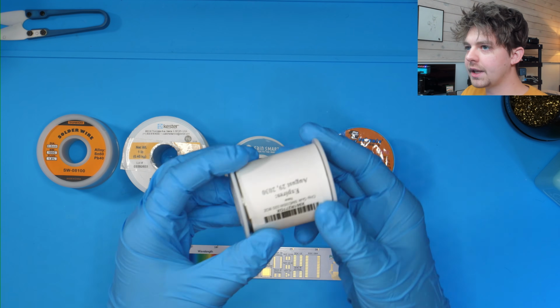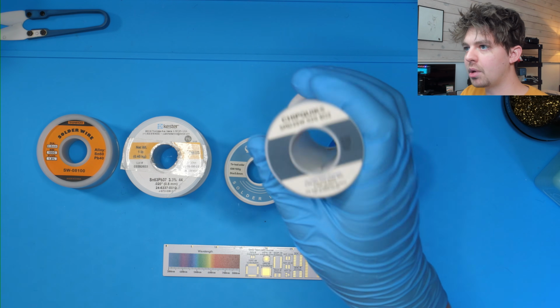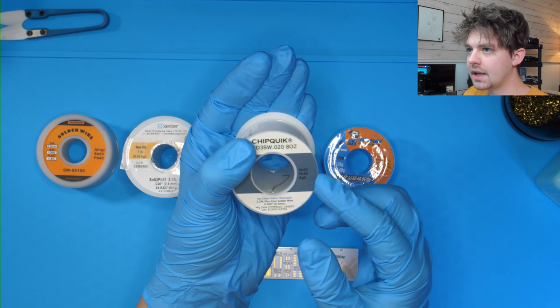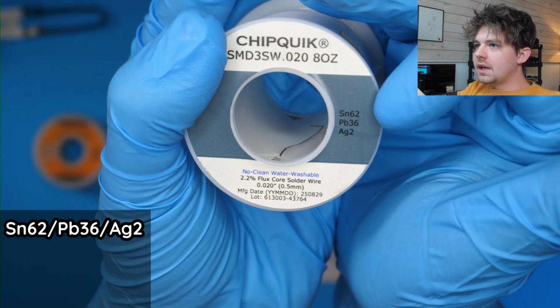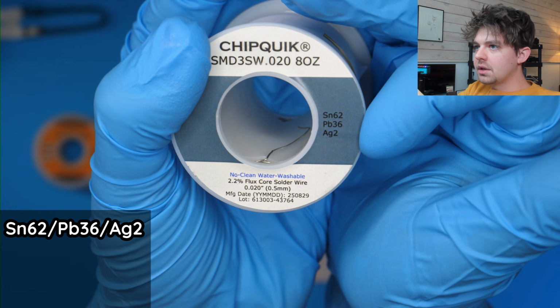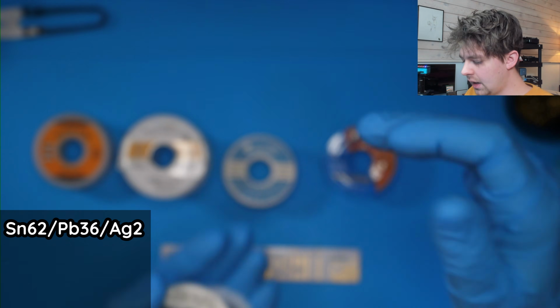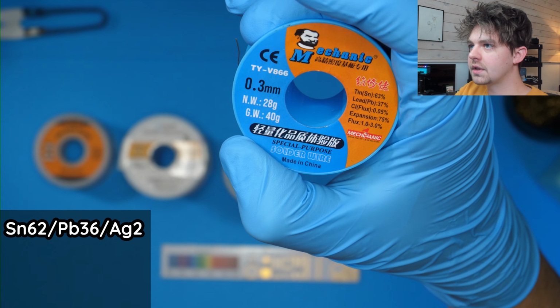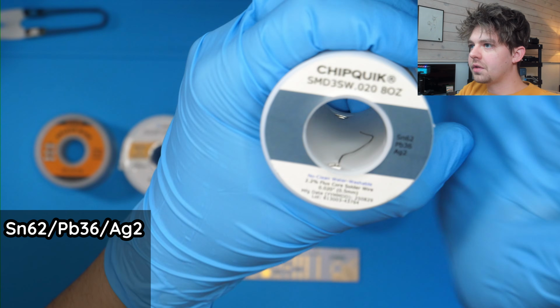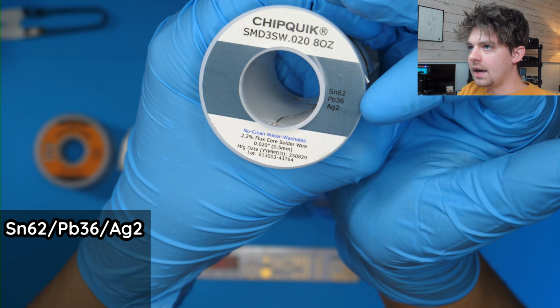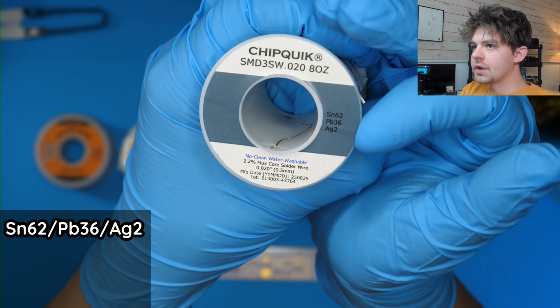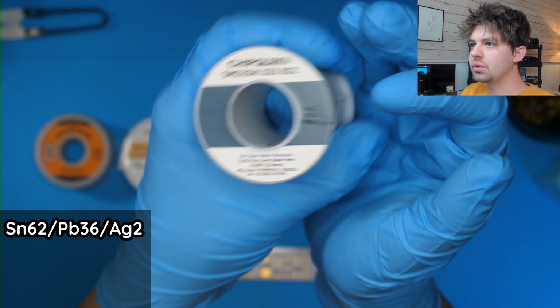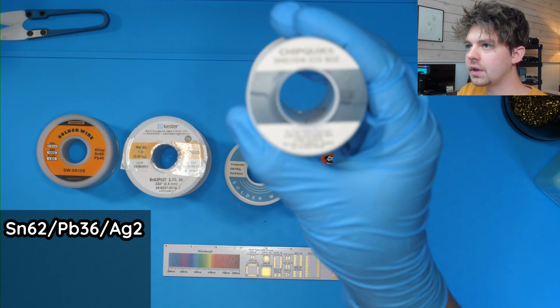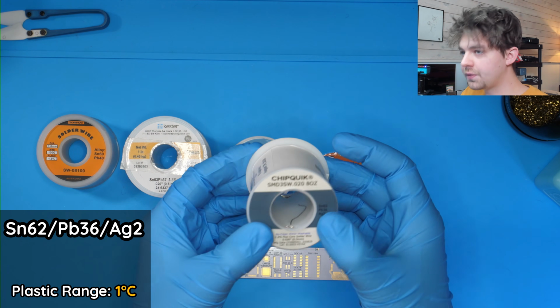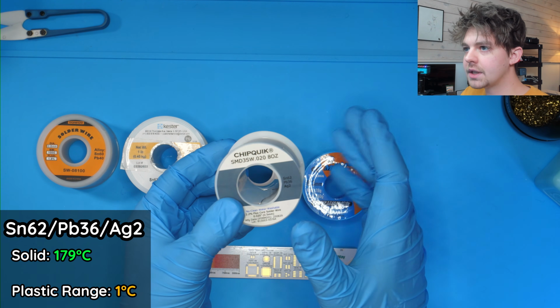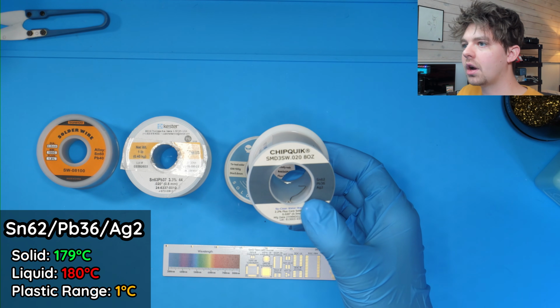And this last one here, I'm really excited to try out. I actually haven't tried this yet. This is a brand new roll that I just bought, and this actually has silver in it. So this one is 62% tin, 36% lead, and 2% silver. And you can see it's a very similar alloy to the 63/37 stuff. So we're just a little bit off on the tin and lead contents there, and that is replaced with the silver. So this stuff is actually not technically fully eutectic. However, it only has a 1 degree Celsius plastic range. So it's fully solidified at about 179 degrees Celsius and fully liquefied at about 180 degrees Celsius.